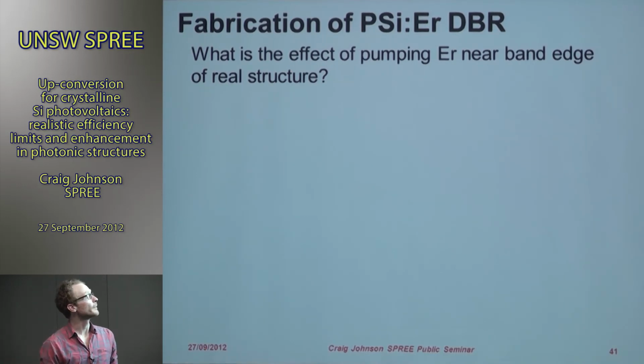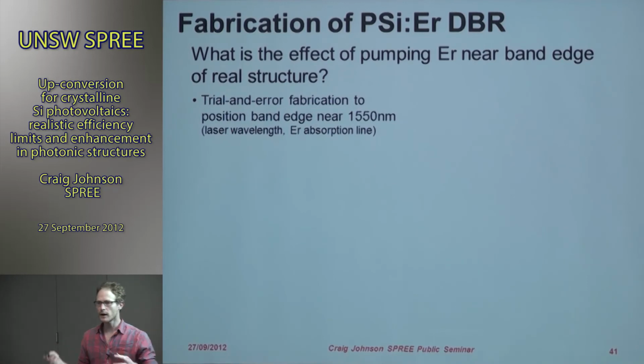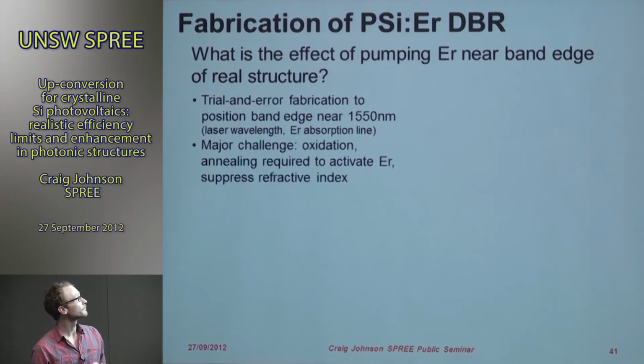So what's the effect of pumping erbium near the band edge of a real structure? Well, through kind of trial and error fabrication over quite a long time, we managed to make a structure that had a band edge near the 1550 nanometer mark. And again, that's the laser wavelength. It's also a strong absorption region of erbium.